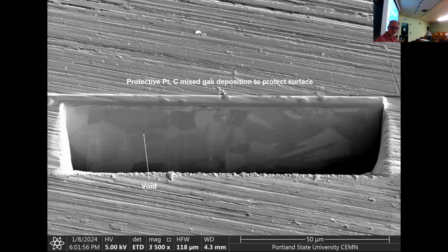And eventually I did a lower current polish, and I come up with this nice little void. There's a defect in that copper. Not surprising. But we can see what we're seeing here in the various colorations. Well, one is curtaining. I did not do a great job polishing this for this demonstration. So that's your vertical striations that can be polished out, and we could make that better for sure. And we can see some grain refinement at the surface, and that's not too surprising because this has been squished between two vacuum components in order to form a seal.